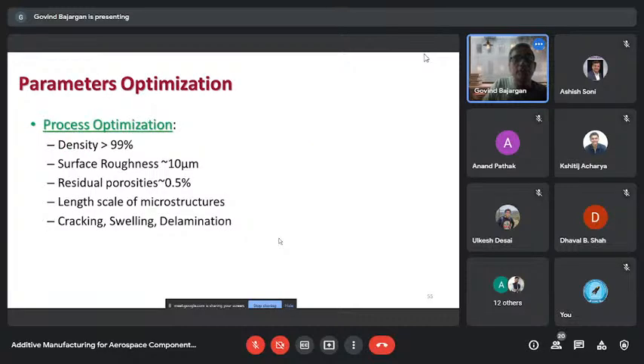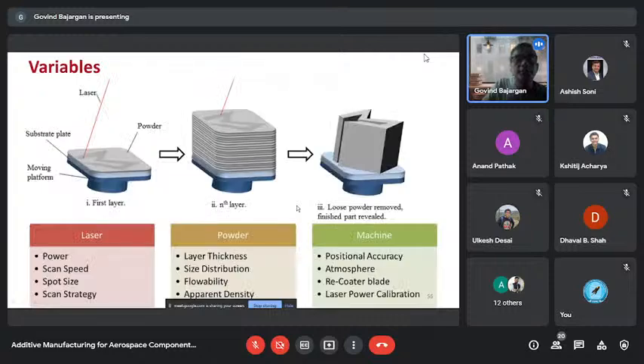So actually for building an AM process like powder bed fusion, what exactly are we looking for? We are looking for density, and I have written 99, maybe 99.5% or higher dense product. Surface finish should be good, of the order of 10 micron generally we can get easily. Then residual porosity should be less than 0.5, and for the length scale of microstructure, we want fine microstructure, and the deposit should be free from cracking, swelling, and delamination.